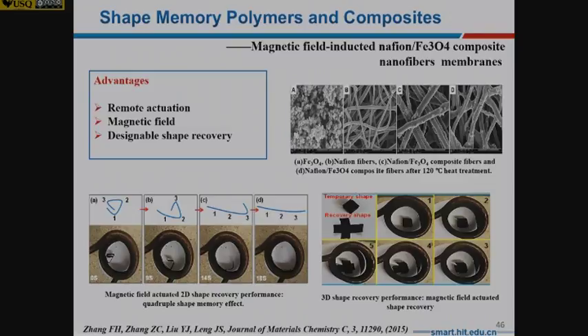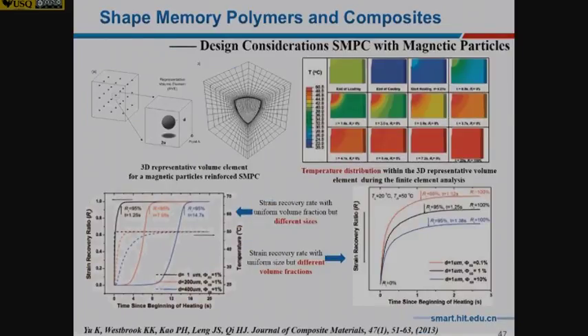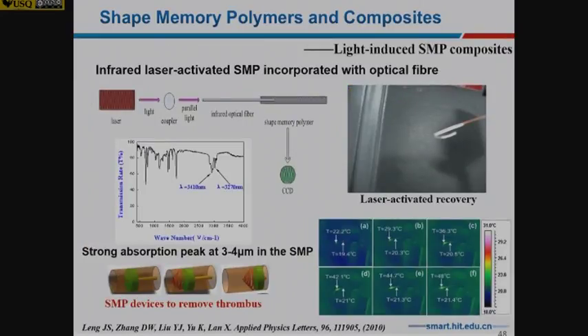Using a magnetic field, because we're using iron oxide, which easily absorbs the magnetic field, this can change the shape. You can see the polymer shape changing from A to D; the shape can deploy and change. So another design, you can design by mechanics, considering different magnetic particle volume and particle size to give you different driving performance for magnetic field driving shape memory. And this is another one where we want to use infrared laser.